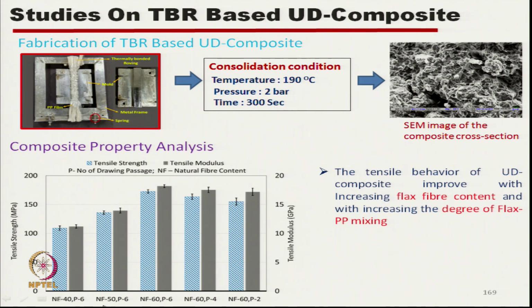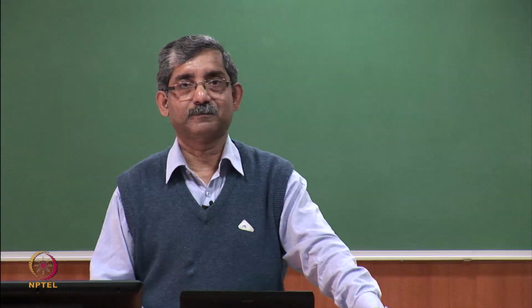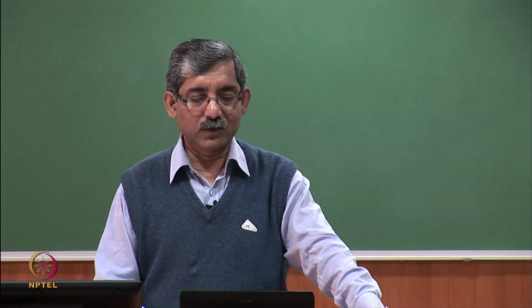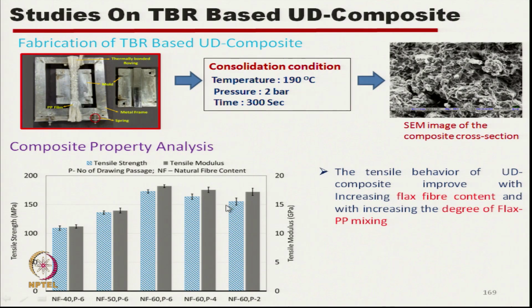Now, once we increase the natural fiber component, we see the tensile strength of the composite increases, which we have already seen for the thermally bonded roving stage. Also, once we increase the number of passages 2, 4, 6, we observed that both tensile strength and tensile modulus increase. The tensile behavior of the unidirectional composite improves with the increase in flax fiber content and with the increase in degree of PP mixing, which is indirectly shown by the number of passages.